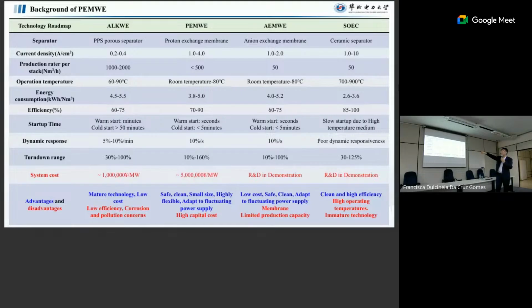For example, 4.5 to 5.5. So this system is a very mature technology, but we have problems. The main problems are hydrogen purity, impurity, and also the electric load. And also today, we try to produce hydrogen directly from the electrolyzers at high pressure. Because we have a porous media, if we increase the pressure of hydrogen, then you will increase the flux of hydrogen to the oxygen part. So that means the ALK system is not suitable for high pressure operation today.